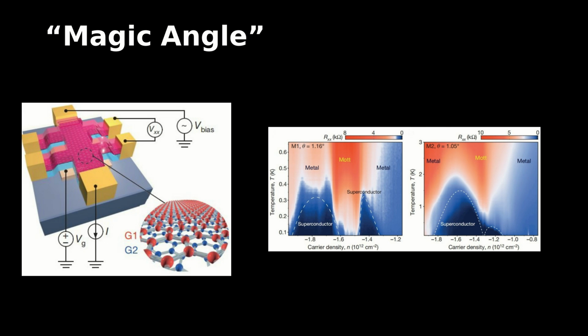It is clear that at low temperature, twisted bilayer graphene can transfer from superconductor to Mott insulator or to metal as carrier density changes. The highest critical temperature for the left one is 0.5 K, and for the right one is 1.7 K.